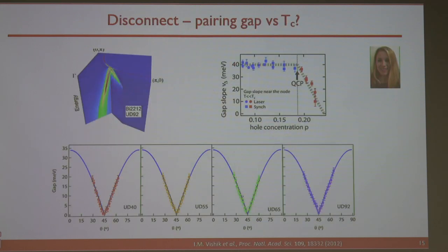Now, if you go a step further and ask yourself, so we have a d-wave pairing, okay? But does the pairing determine the Tc? For a d-wave superconductor, the most sensitive measure of the superconducting gap is the gap near the node. This is particularly true in cuprates because, remember I said earlier, there are other instabilities competing with superconductivity, and that could also create a gap. Okay? But we know the node is the superconducting gap.